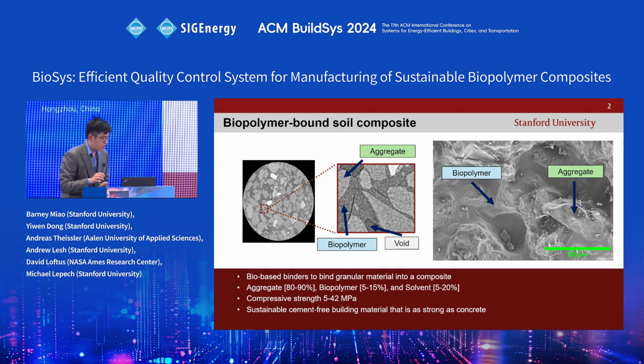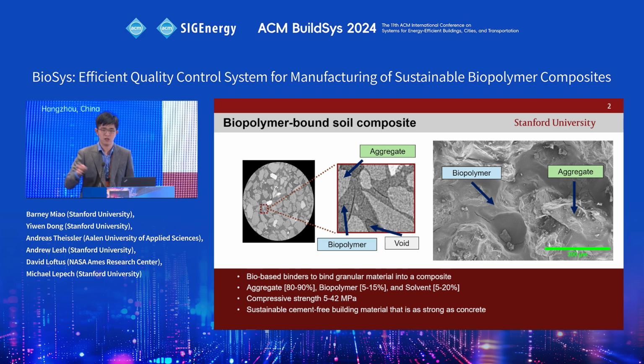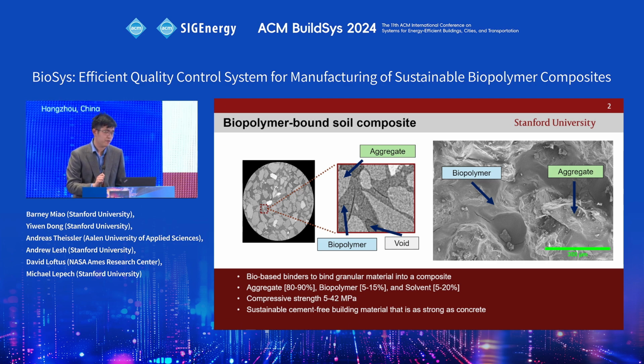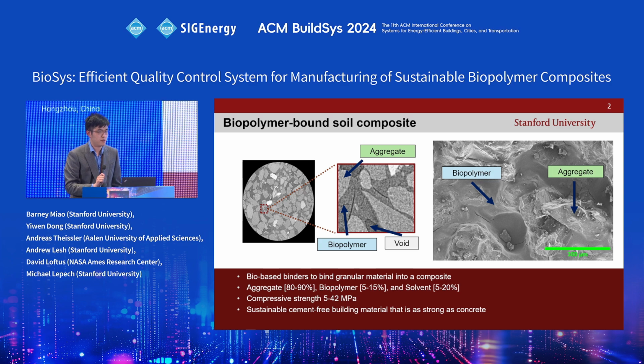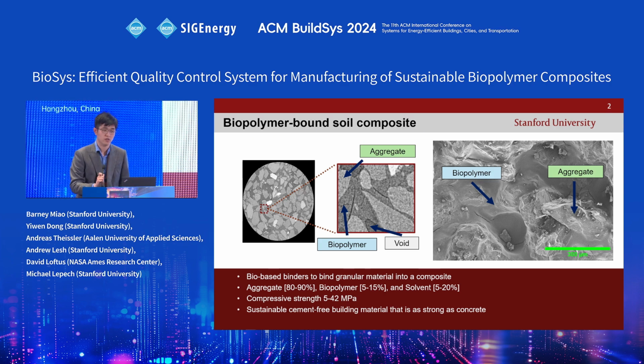The composite is generally 80 to 90% aggregate, also known as soil: any soil, sand, anything you could think about. The soil is not that important. The rest is the biopolymer itself and also a solvent. The strength of the material is around 5 to 42 megapascals, and for reference, concrete itself is around 20 megapascals at least, so it is as strong as concrete.